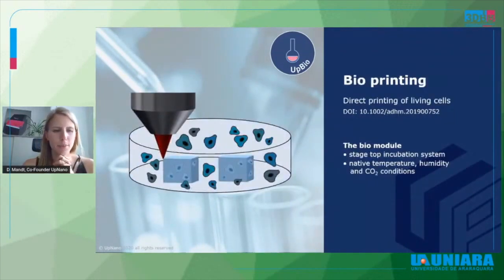The next possibility with biological applications would then be the real bioprinting approaches, we're calling it. So really embedding the cells into the material. This is done then with the Biomaterial. This is a material which came as a kit, as I said before. So you prepare the cell solution with the cells of choice, then mix it together with our monomer and the photoinitiator, and then the cells are really distributed in this material. And when printing, the material is hardened and the cells are then therefore embedded in the structure. And after the printing process, the remaining cells can be washed away.